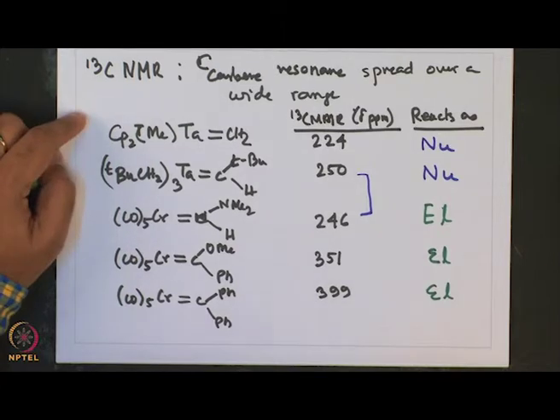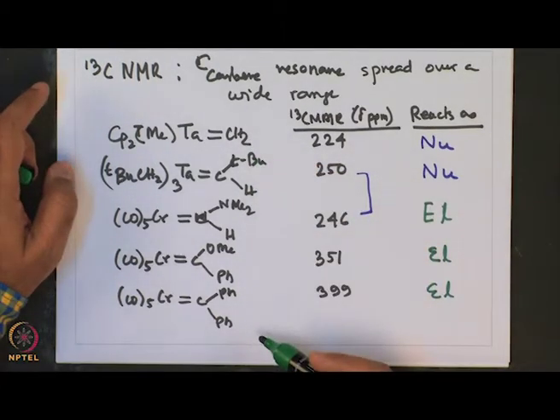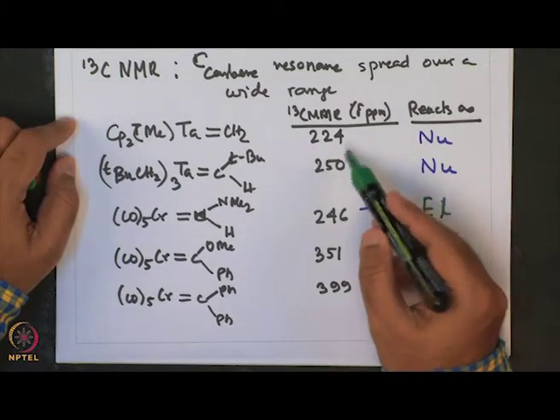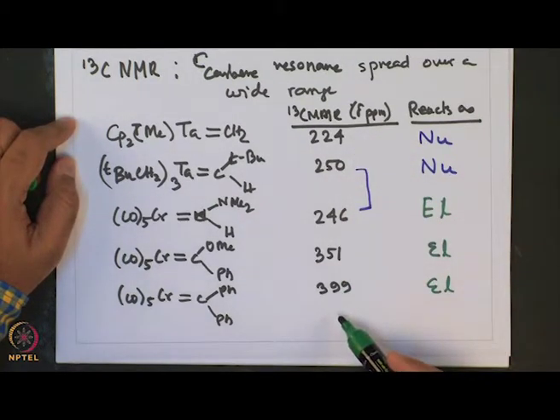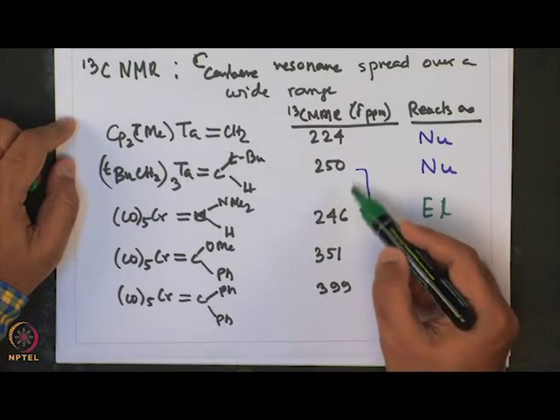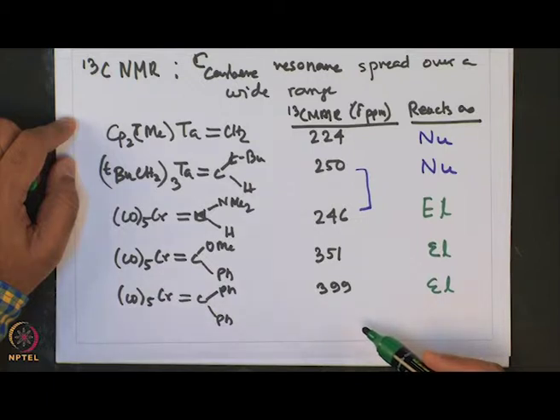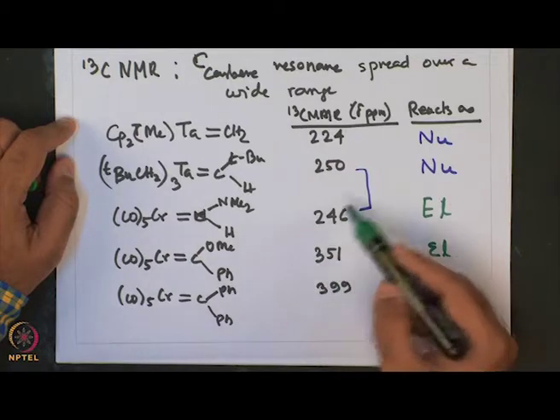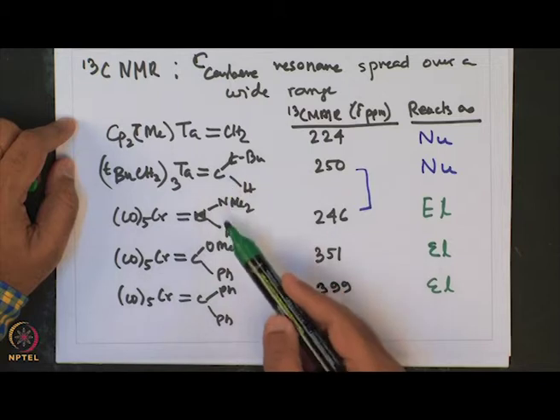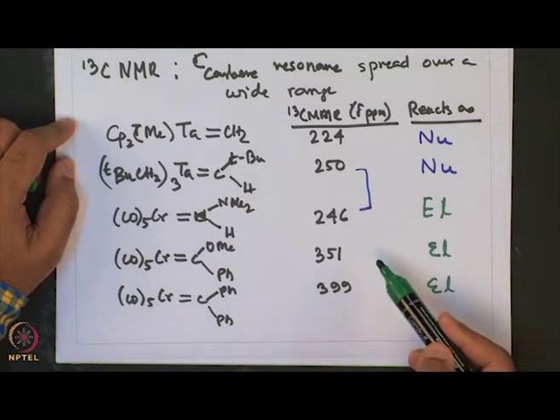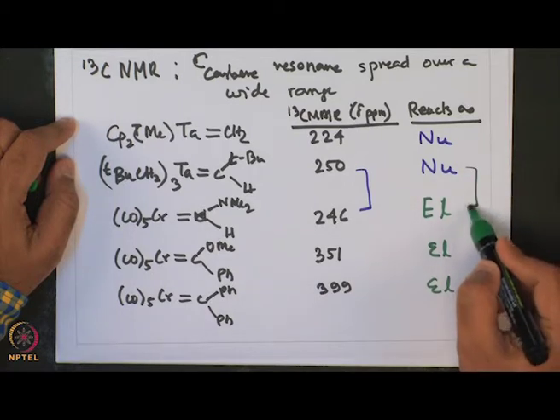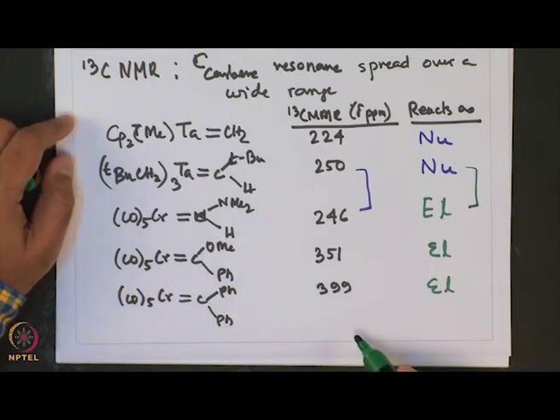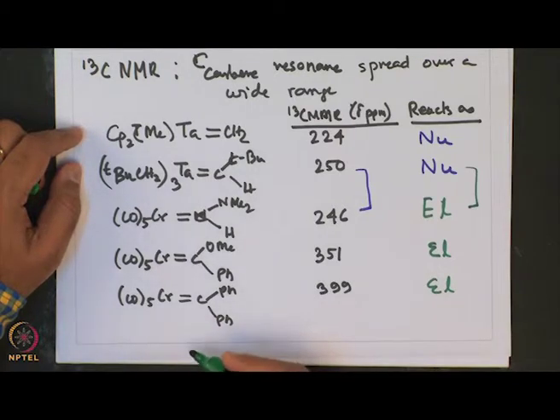So, one can conclude that the carbene moiety appears in a wide range from 220 to about 400 ppm, and they can appear in any part of this range, and it is very difficult to predict the reactivity just based on the carbon chemical shift, because we can have a Fischer carbene or a Schrock carbene showing almost equal chemical shift but showing extremely opposite reactivity. So, this is consistent with the fact that the carbon resonance indeed varies a lot.